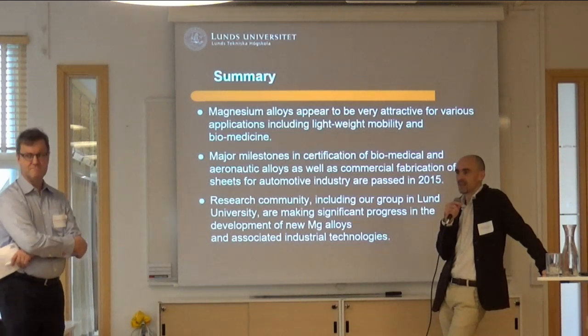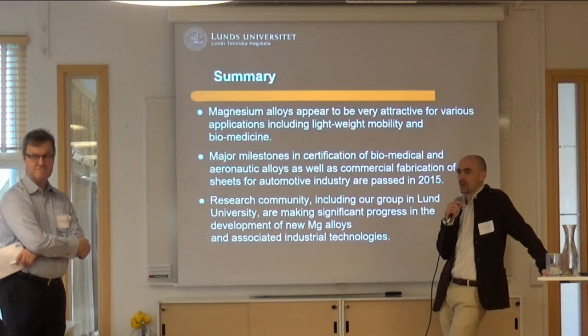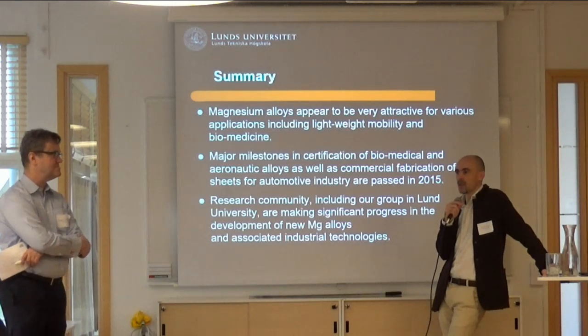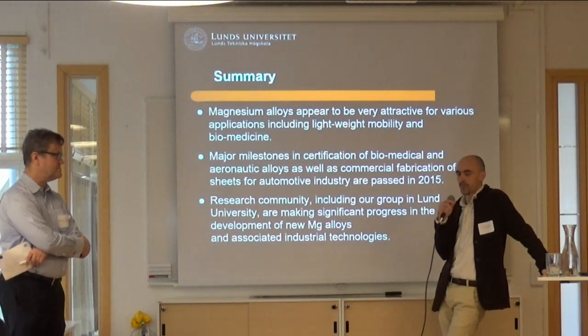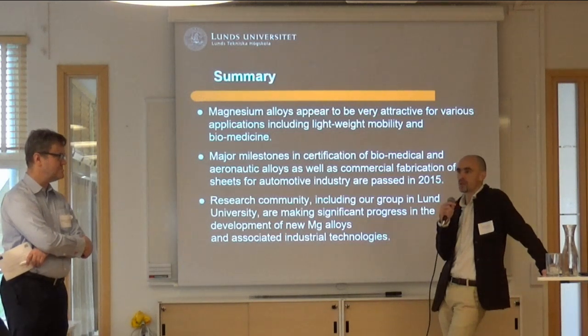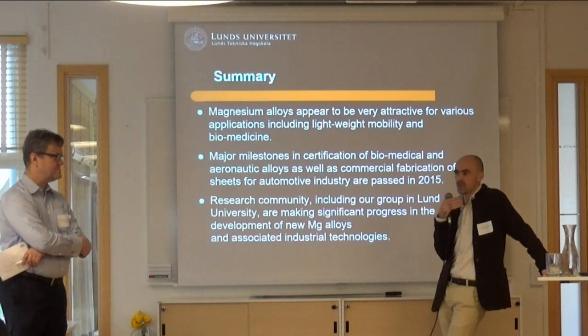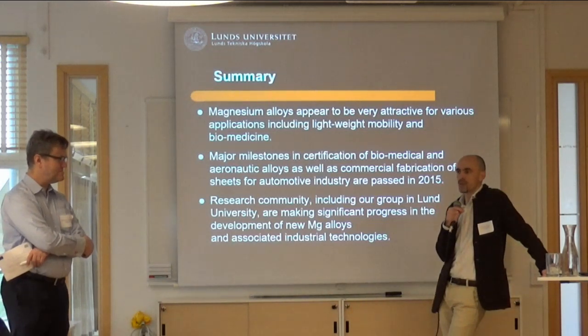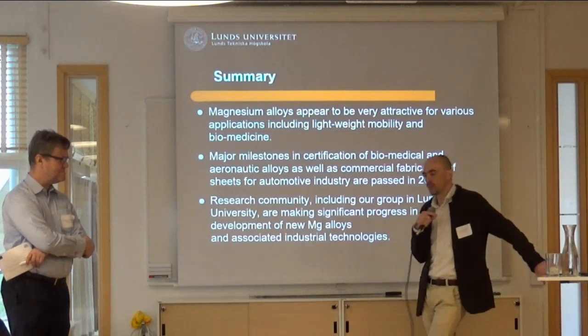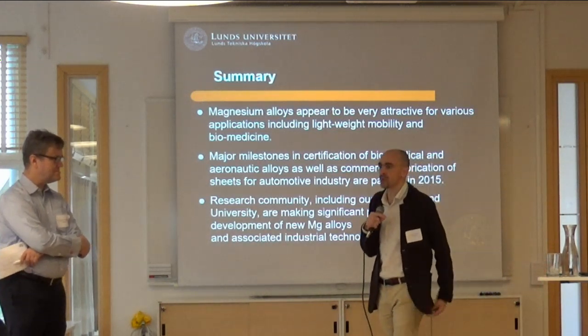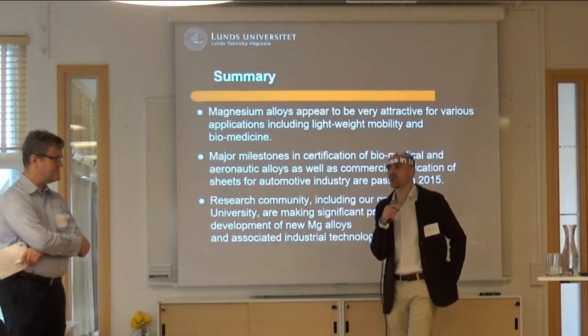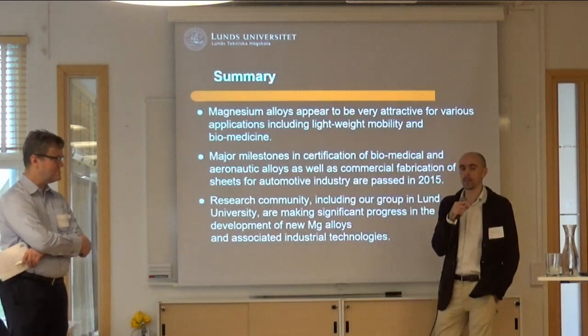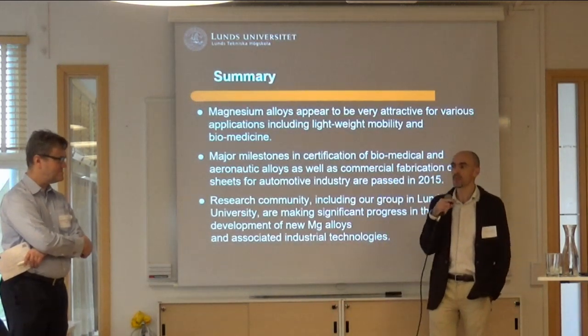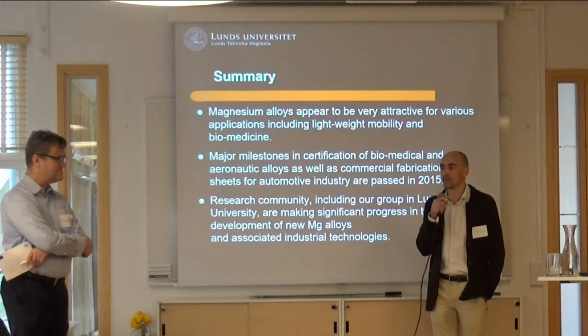It's not only electric coating and painting, at different temperatures. Plasma oxidation is for biomedical applications, where you cannot coat it with anything. You want to achieve bulk corrosion, well controlled at an even rate. But in the car industry, there are some efficient coatings. Again, there is one of the groups in the Magnesium Innovation Center that works on efficient coatings. They developed a kind of active coating that has been shown to be very efficient.